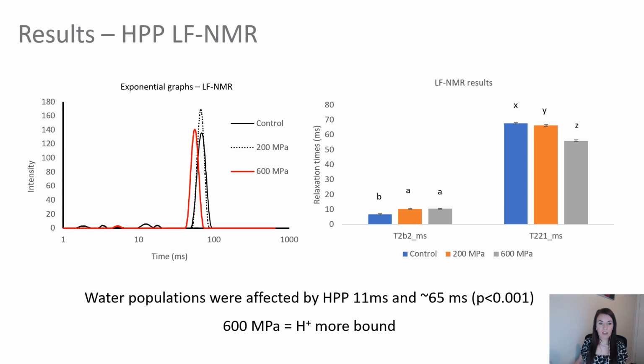So then we applied low-field nuclear magnetic resonance to understand the water binding within the gel matrix. And as you can see on the graph here, the red line has a peak which is coming in shorter than the others, and that's corresponding to 600 megapascals. And on the bar chart, the grey bar shows that that relaxation time is significantly shorter. So what this indicates is that the hydrogen ions, those which are present in water, are more tightly bound within the gel matrix or more entrapped. So this indicates that we're getting improved water binding with the soy proteins after 600 megapascals of high pressure processing.